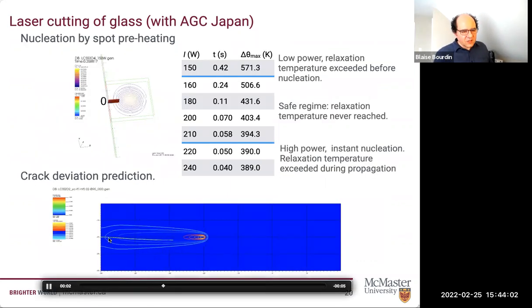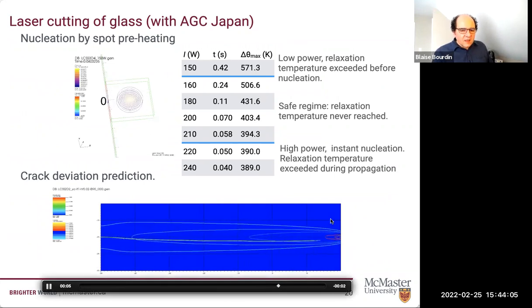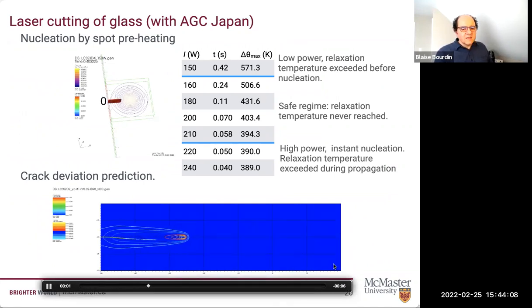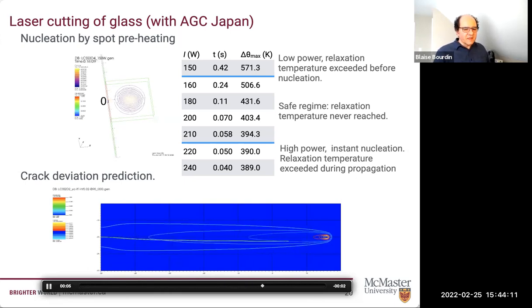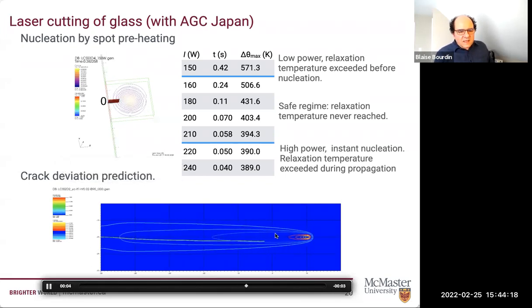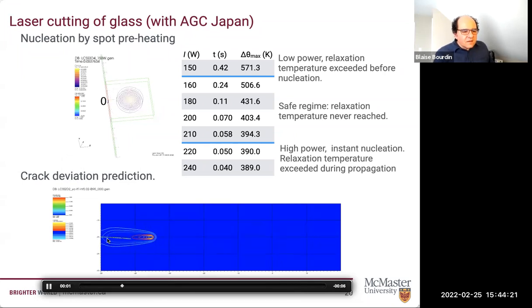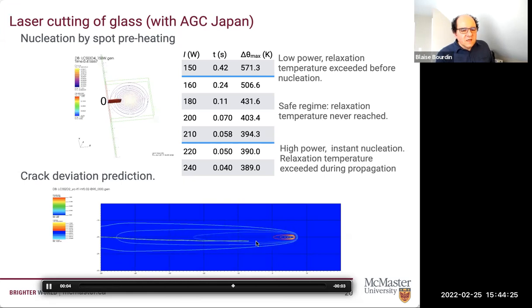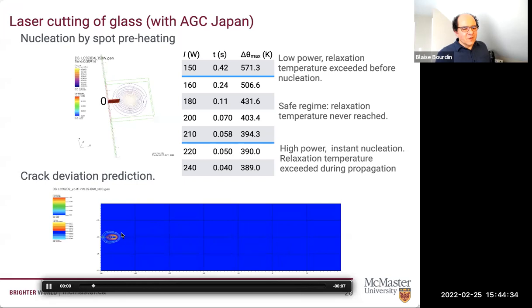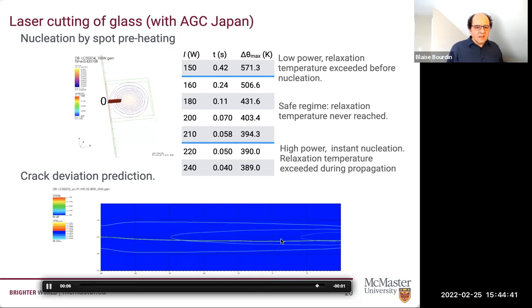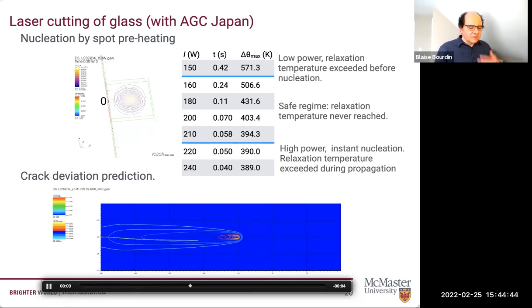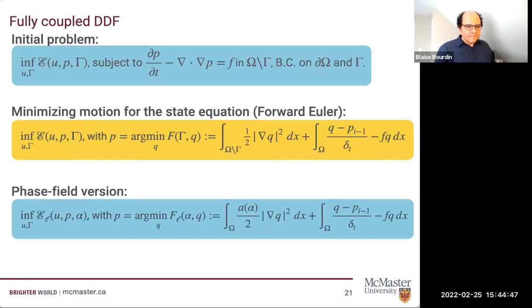And okay, I'll just talk about this picture, but this is an example. What I'm showing here is just one little piece of a very large domain. And I've been trying to grow a crack through laser cutting close to the edge. So the lines are the contour lines of the temperature field. And this curve is the crack. And what you see is that we can predict the deviation of the crack path numerically. Of course, the next step is the inverse problem: where do we want to move the laser beam so that the crack, for instance, grows along this straight line? And this is clearly a complicated and open problem, but something, in my opinion, very interesting.